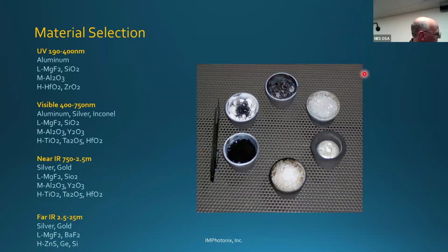In the visible, you still have the same materials, but we added titanium dioxide, tantalum oxide, and yttrium oxide. They absorb in the UV, so they're not classified as UV film materials. And then in the infrared, out to about 2.5 microns, the same materials apply. We have to be careful when we start working in the near infrared and far infrared because of absorption bands. If you look at the radiation spectrum, and especially with oxides, you'll see around 2.5, 3.5 microns, and I believe around 7.5 microns, these films will be highly absorbent in those spectral regions. If you're outside of those spectral regions, you get away with the use of some of these oxides. But to be safe, we tend to stay away from them.